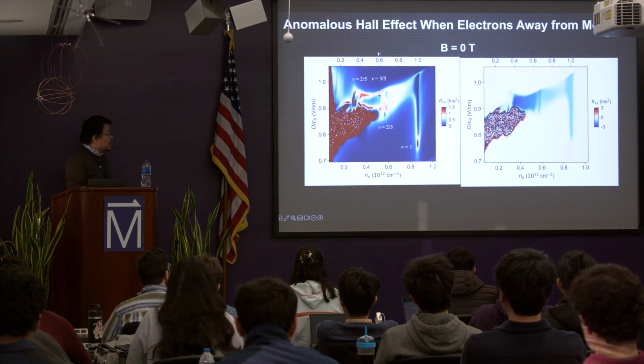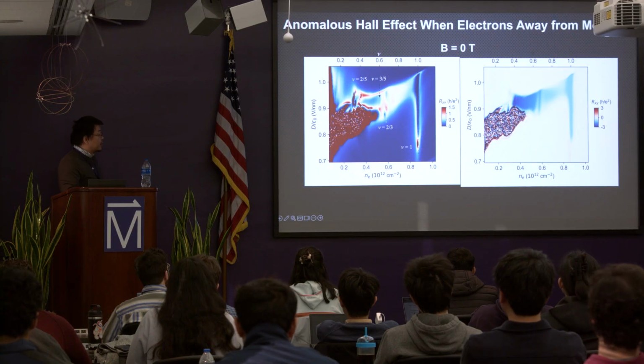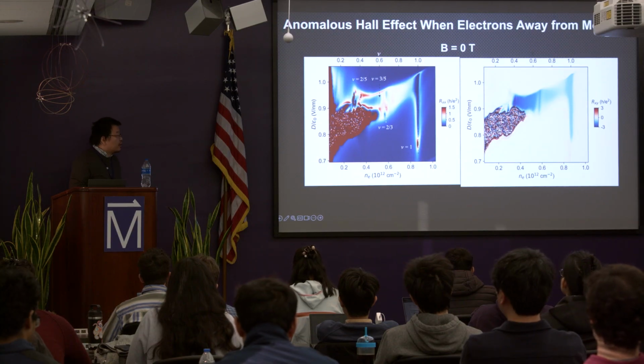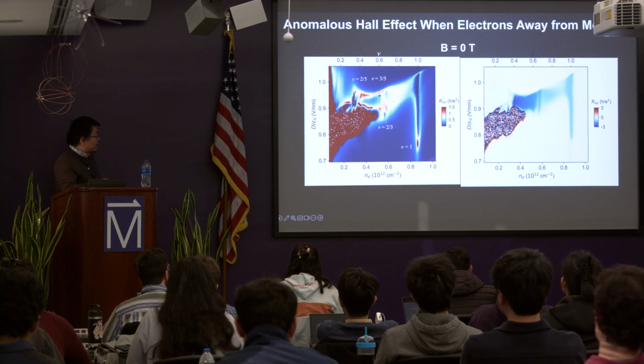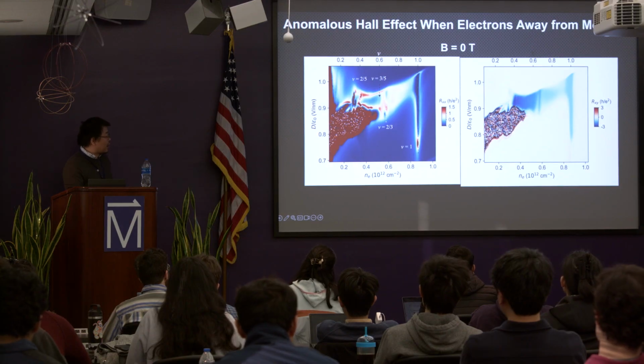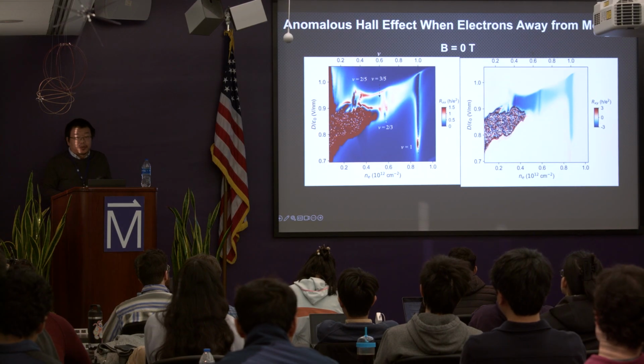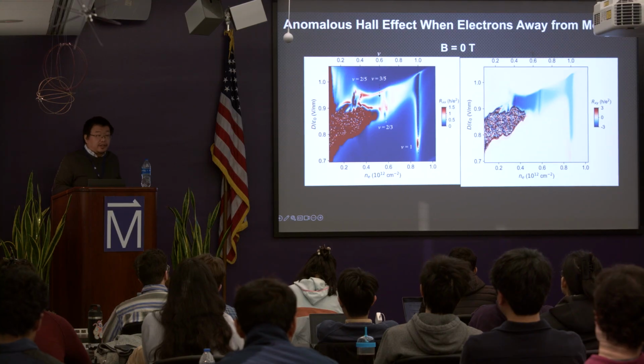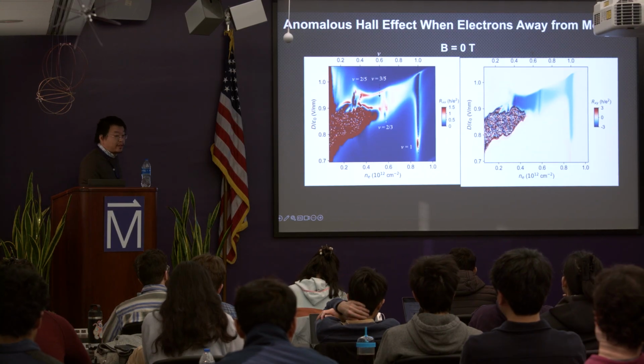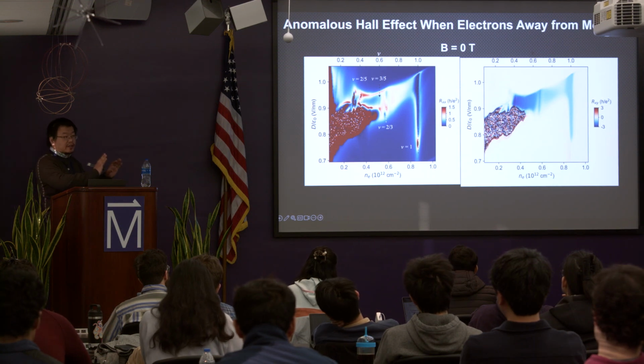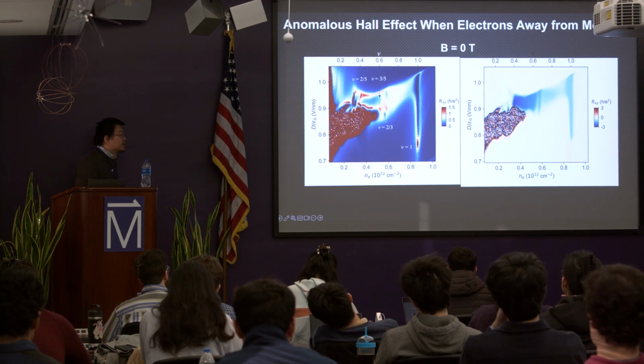From this color plot, you can already see a lot of abnormal things. First, a pretty important thing is that the electric field is almost 1 volt per nanometer, which is really high, and close to the breakdown of the dielectric. So basically, that means I really push hard the electrons that are far away from the moire potential.